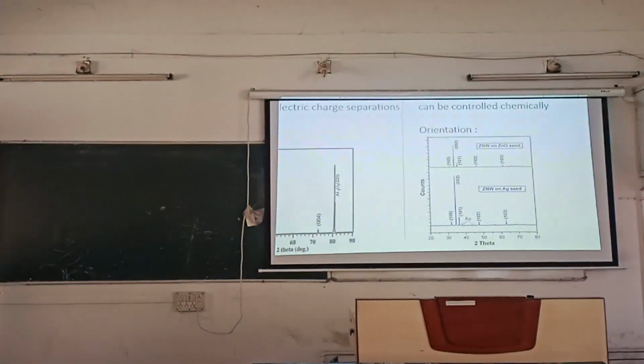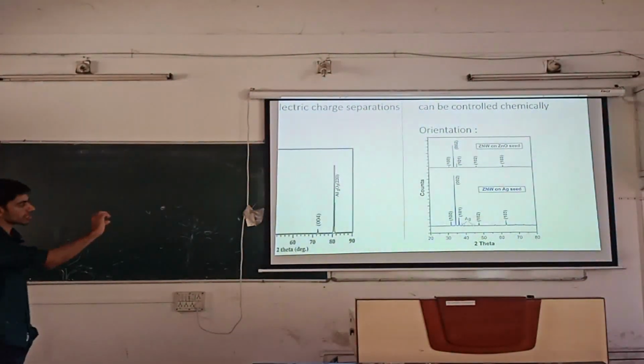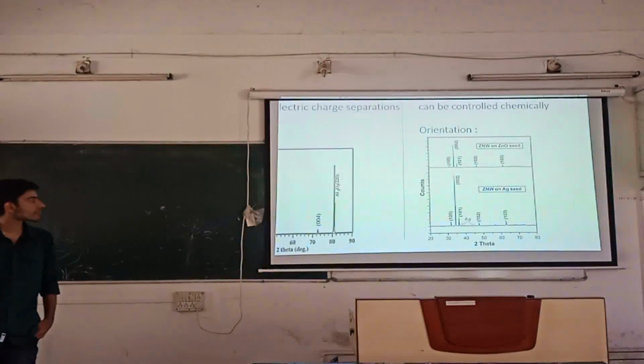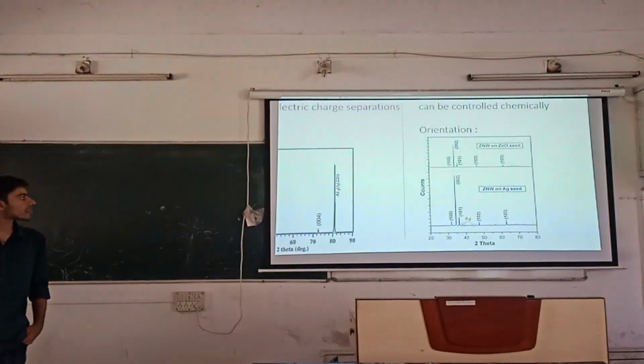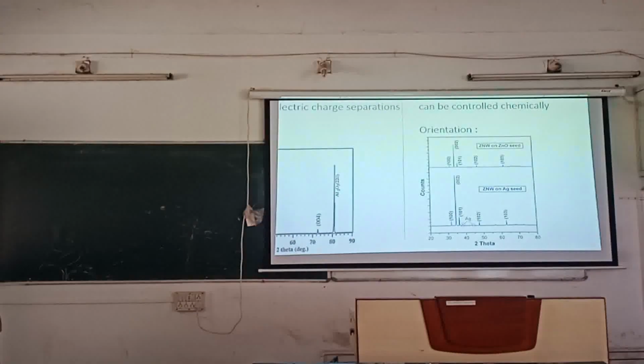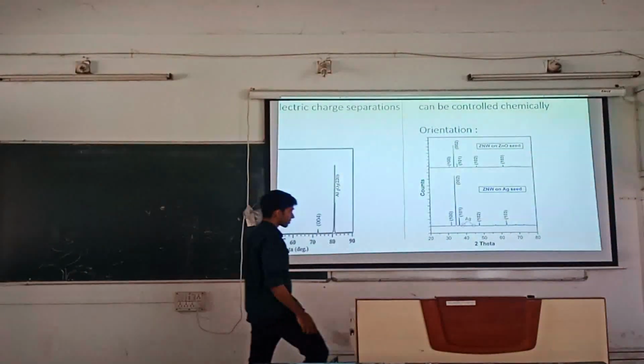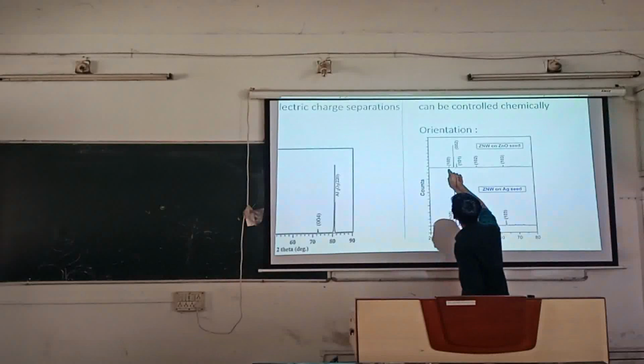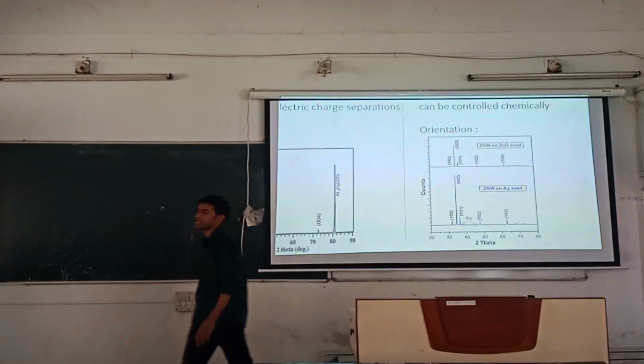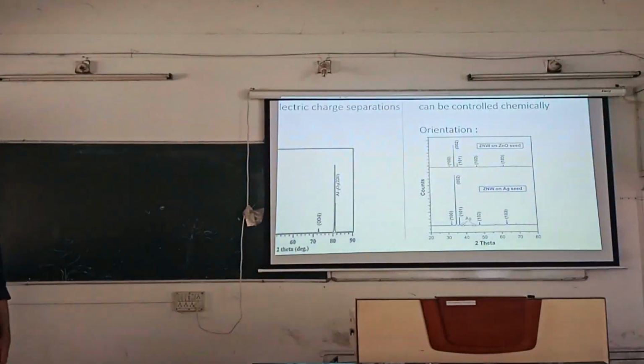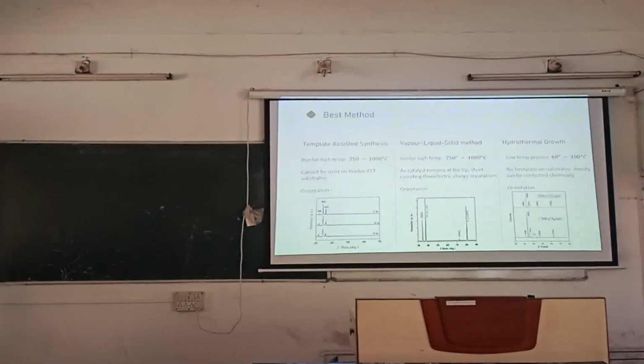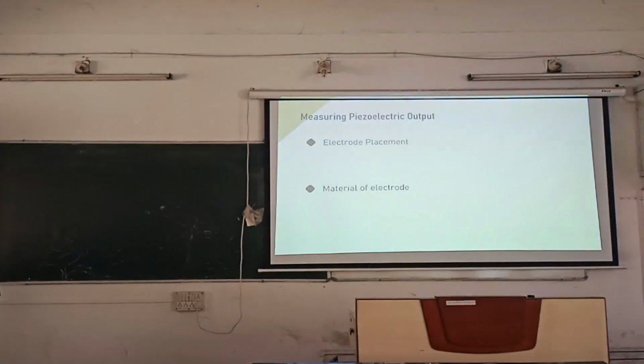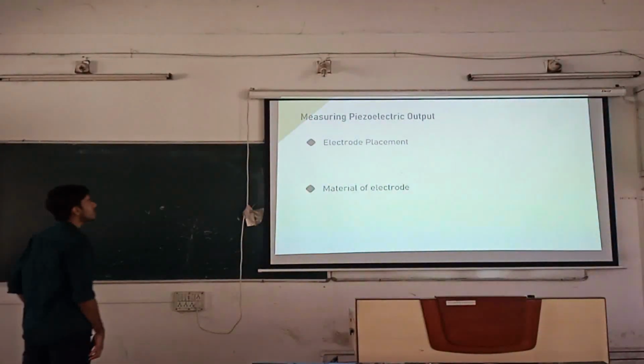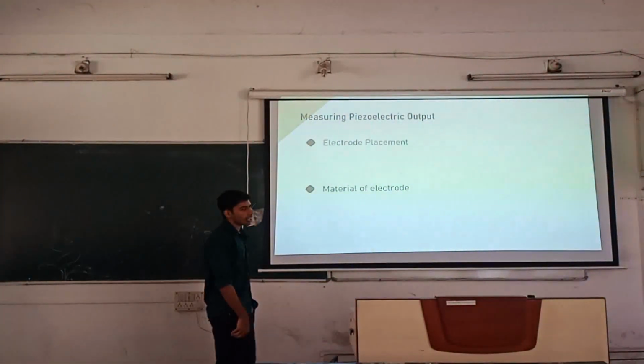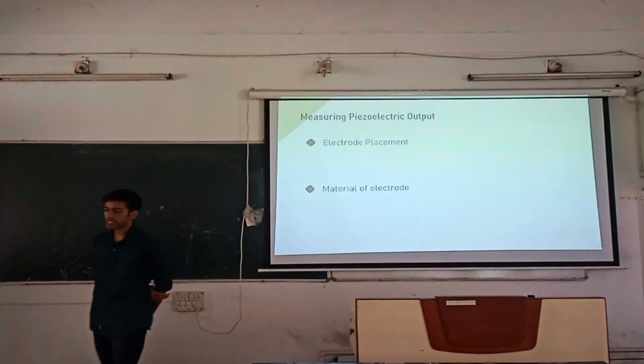And then there is the hydrothermal method where 002 is very prominent, but there are other small peaks corresponding to silver and all. But that is okay. Silver seed, zinc oxide seed, you can see on the top. All other peaks are very small. Only the 002 peak is huge. So in our lab, we will be using this hydrothermal method to grow the nanowires. So I'll show you my research work later.